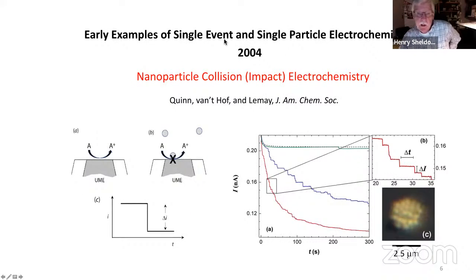And then about 10 years later, another hallmark paper came from Bernadette Quinn and Serge Lemay on looking at the collision and absorption of polystyrene particles on a small microelectrode. And the experiment is set up by, you have molecule in the solution, something like ferrocene again, and it's being oxidized at diffusion limited rate. And then one of these insulating particles absorbs on the surface, and it partially blocks the flux of the molecule to the surface, and you see a decrease in the current.